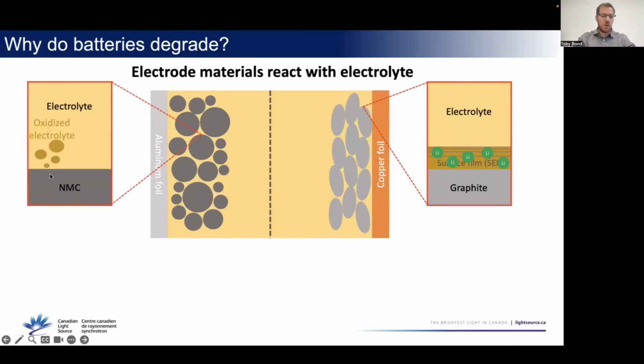On the positive electrode side, you also have reactions at the surface, but they tend to be a bit different. One of them is something we call electrolyte oxidation. This tends to happen at higher voltages, so higher states of charge. You can also, in some cases, have gas formation, so you can have oxygen or other gases evolved at the surface. And the third reaction that's concerning is what we call restructuring or rearrangement of the cathode of the NMC. This happens at the atomic layer, and the problem with this layer is it hinders lithium ions from actually getting across into the electrode, into those spaces where it's stored. This slows down and makes charging slower. It means that you don't get as much capacity that's accessible to the battery. And so these are all surface reactions.